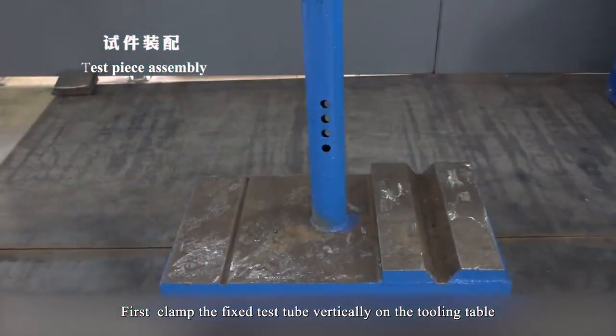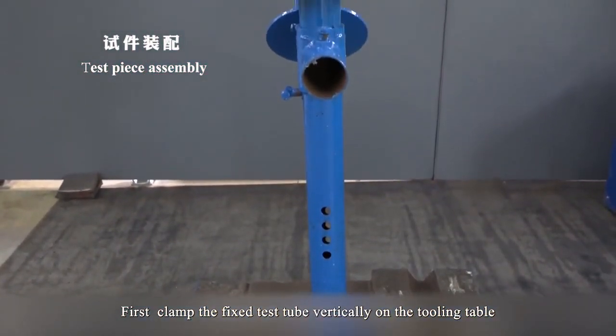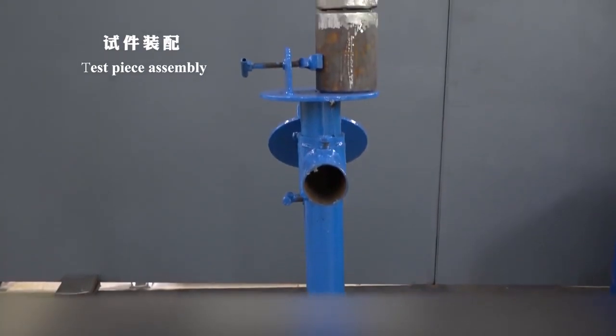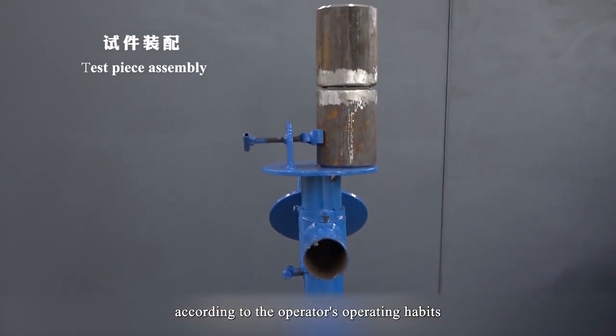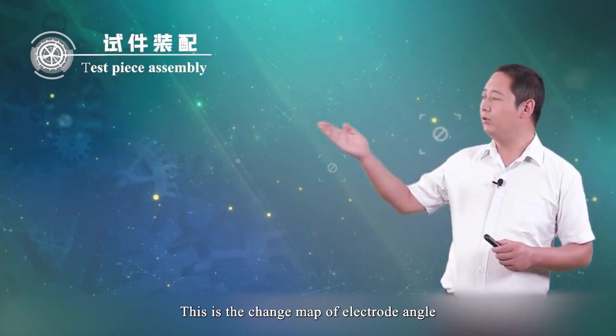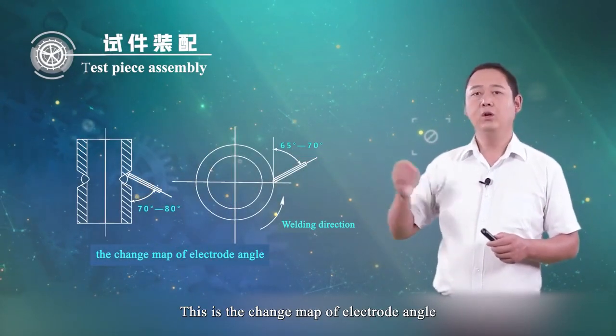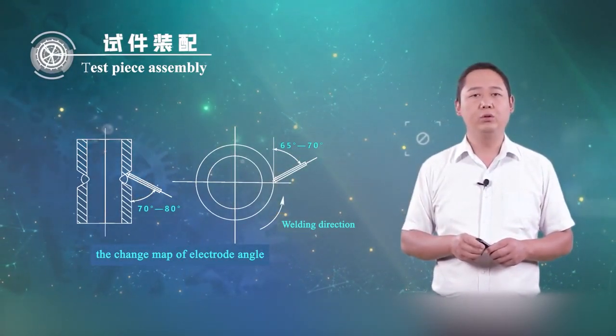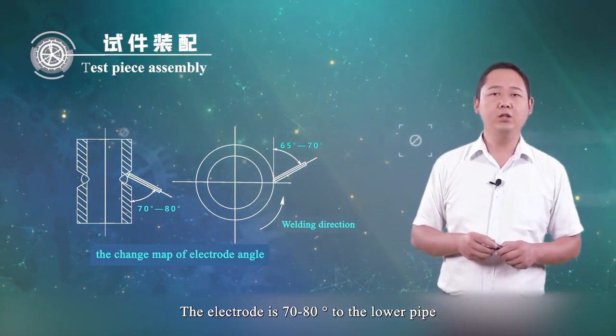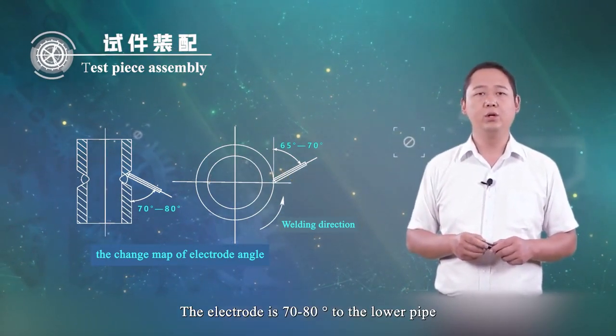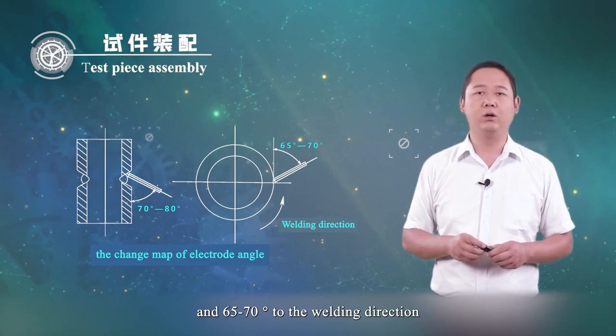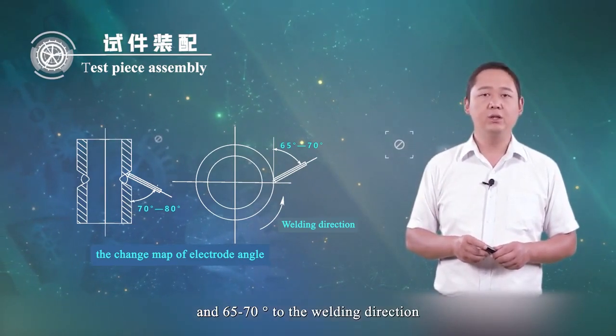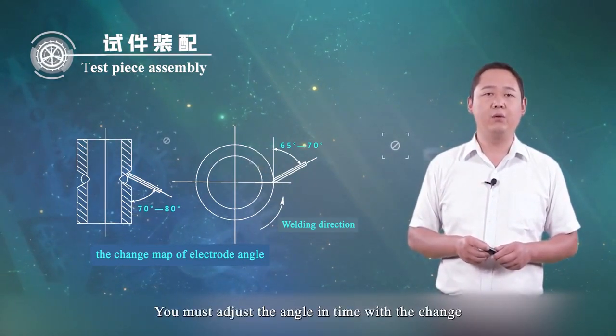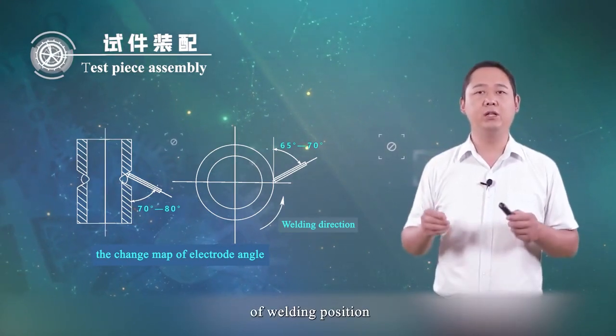First, clamp the fixed test tube vertically on the tooling table according to the operator's operating habits. This is the change map of the electrode angle. The electrode is 70 to 80 degrees to the pipe and 65 to 70 degrees to the welding direction. You must adjust the angle in time when the welding position changes.